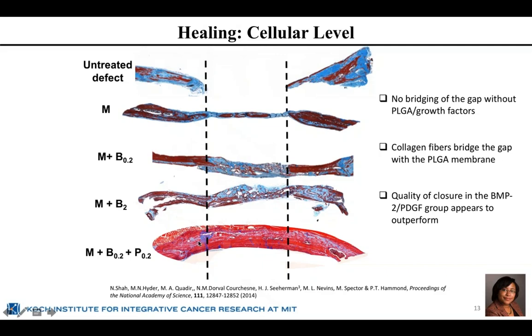And we think what happens here is that we are supporting first the generation of blood vessels across this material matrix, and second, the recruitment of these bone progenitor cells, which then begin to deposit mineral around the vascular system. The fact that we have blood vessels not only provides a more oxygenated and healthy bone, but also promotes the progression of osteoclasts, which are the cells that remodel tissue, to arrive and remodel the bone so that we get this very nice, highly oriented bone in this case.